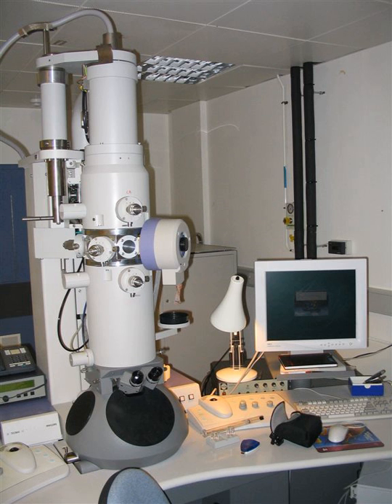Embedding, materials. After embedding in resin, the specimen is usually ground and polished to a mirror-like finish using ultra-fine abrasives. The polishing process must be performed carefully to minimize scratches and other polishing artifacts that reduce image quality. Metal shadowing. Metal, e.g. platinum, is evaporated from an overhead electrode and applied to the surface of a biological sample at an angle. The surface topography results in variations in the thickness of the metal that are seen as variations in brightness and contrast in the electron microscope image.